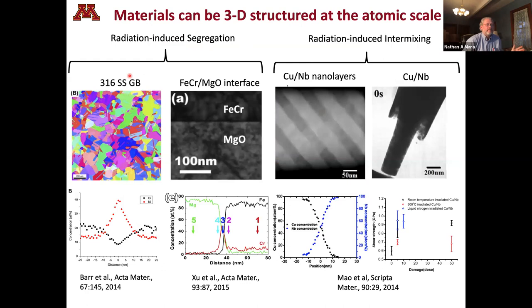Radiation-induced segregation is one example. You stick a bunch of 316 stainless steel into a nuclear reactor, which is a workhorse material in a nuclear reactor. What happens to the grain boundaries? Well, you'll start to enrich nickel, and you'll start to deplete chromium. And that affects both the corrosion properties and also the mechanical properties of these materials. You can do this to ceramic intermetallic interfaces. Same kind of things happen. You get either depletion or segregation to those interfaces.